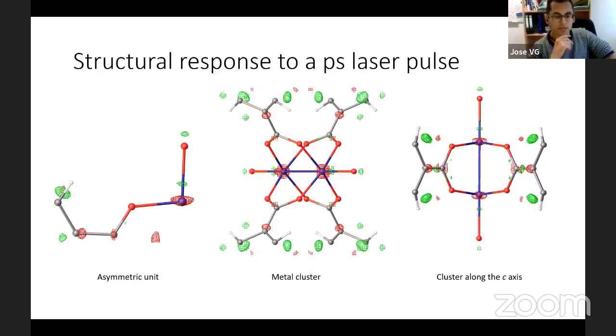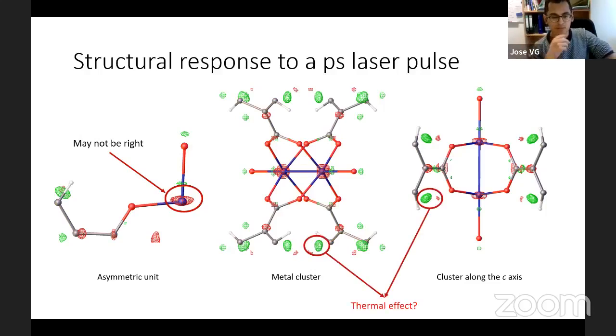However, I have done some more refinement and obtained different structural maps, and now I think that this change may be false, may be caused by some spurious reflections obtained during the experiment. However, there is something that always remains there, and this is a green area close to the carbons or close to the oxygens. So regardless of how I treat the data, how many times I process the data, this seems to be a constant. And this green area next to the carbons may mean that the carbons are the ones that are changing after light irradiation.